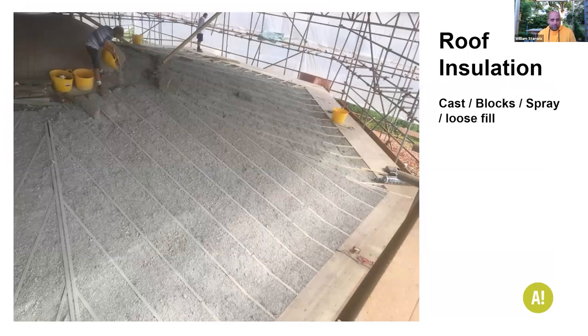Roof insulation. We use a lower density mix for better insulation where the strength is not required. It can be cast, sprayed, blocks or dried loose fill insulation. Here we've got low density blocks laid out on the roof, and then we're using a dry loose fill hempcrete to fill in the gaps.